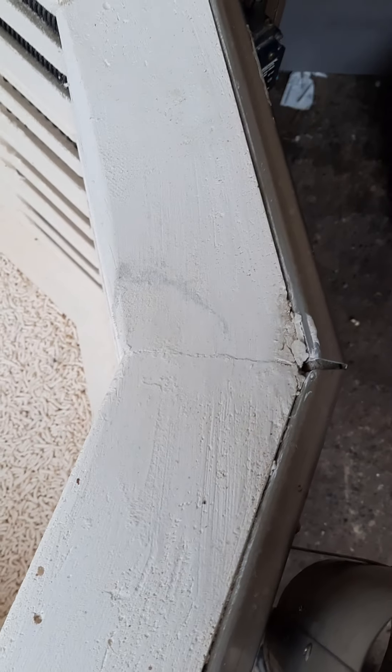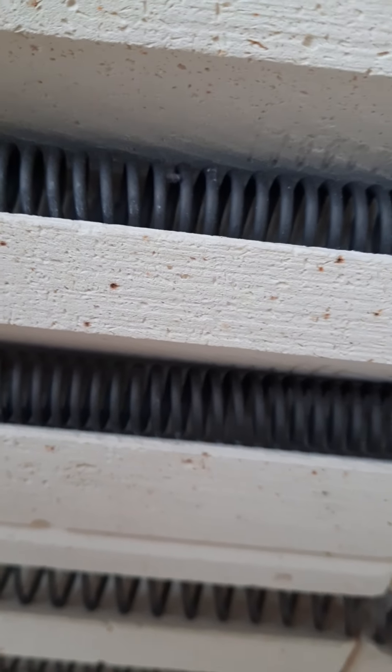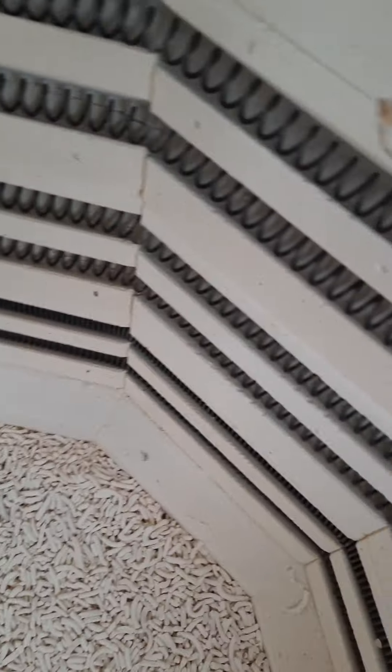The jacket has been taken off and the clamps tightened. As you can see, all the bricks are level. There was a little bit of crumbling due to moving, which has all been re-cemented. The elements are all brand new, so you will need to re-season this kiln to 1100 degrees Celsius. As with all Cromartie workhorses, this kiln has vermiculite on the bottom, so you'll need to put a large shelf down before loading anything else.